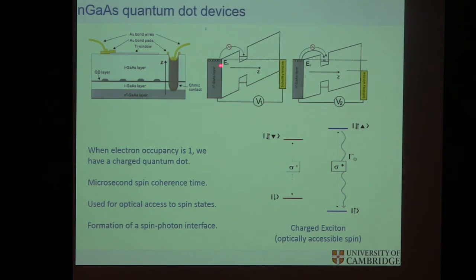And then by applying a voltage, you can basically tune the energy diagram of this whole system, almost like a lever arm. So with the voltage you apply, you can either deplete any electron in the conduction band, or you can allow one electron in if you apply the right voltage. That range, where from one end you have no electrons in the quantum dot, and on the other end you finally have 2 electrons in the quantum dot, due to spin degeneracy, for example, but enough energy given to the quantum dot to fight the Coulomb repulsion. The capacitance is very small. That range is about 150 millivolts or so, so it's very comfortable in the lab to actually be in that single electron occupancy regime deterministically.